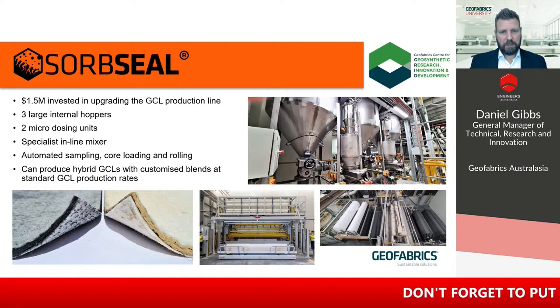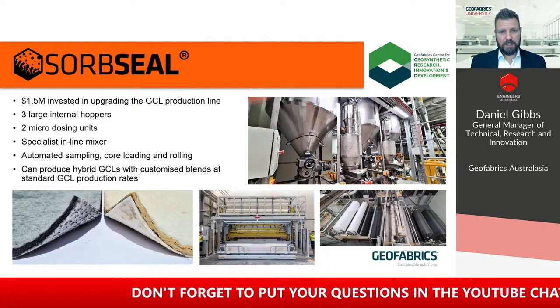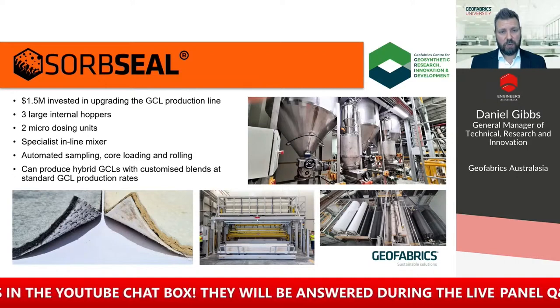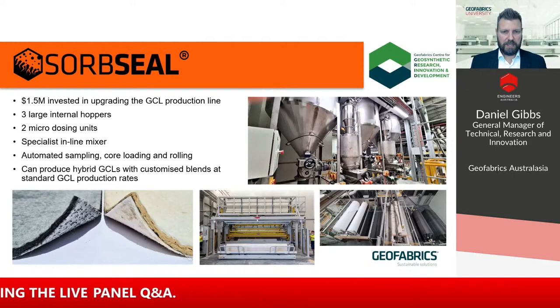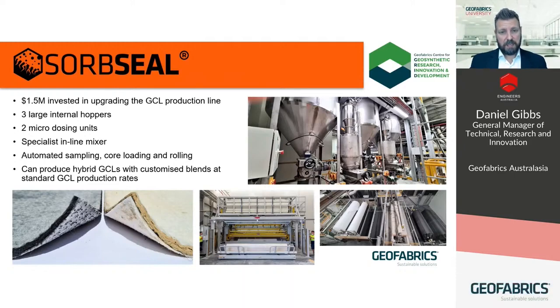So once we selected an activated carbon with the right properties and the right particle size, then we had to figure out how to manufacture with it. Prior to us spending around $1.5 million on upgrading the equipment, we ran several small laboratory trials and then larger scale online trials to qualify the product and the amount of activated carbon required to get that right balance between PFAS adsorption and GCL permeability using landfill leachates. So when it came to designing the equipment, we knew how much activated carbon we wanted to have per square meter, how we wanted to mix it, and whether we wanted a selection of other potential materials to be added as the body of research around PFAS transport and materials science grew, both in our lab and generally around the world.